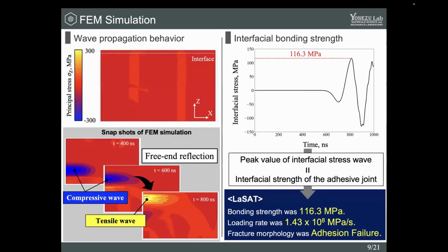This is the wave propagation behavior of FEM. The contour map displays the stress component in the Z direction. First, at the beginning of propagation, a compressive wave was generated. Then, when this wave reaches the free surface of the FEM model by free end reflection, this wave turned into a tensile wave. This behavior of FEM was similar to that explained in the overview of LASAT. Then we obtained the interfacial stress at the center of this model.